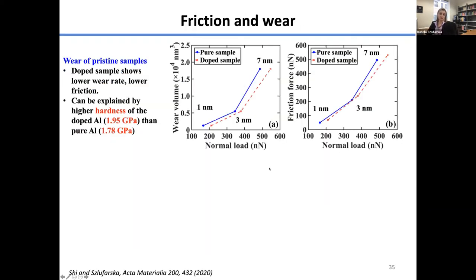Okay, so what we did, we performed simulations, just started with single asperity sliding. We simulate a tip, and we slide it across the sample and we measure the friction force and the wear volume as a function of the normal load. This is just on a pristine sample. It was a clean sample, we just made it, and then we slid for the first time. And what we found is that the pure aluminum sample, which is the blue color, has a higher wear volume and higher friction than the doped sample, okay? And the reason for that is consistent with the hardness of the samples that we measured. So we found that the doped sample is slightly harder than the pure sample in this case, okay?